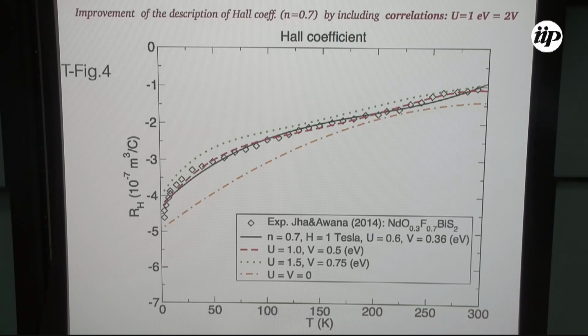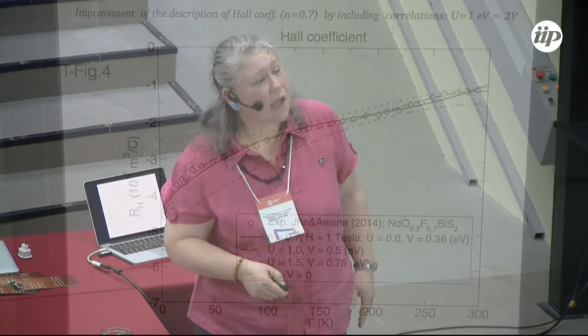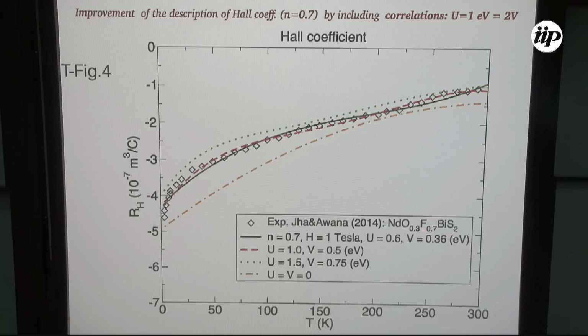Let me show you the kind of Hall coefficient results we're getting. Here the orange dot-dash curve is for the uncorrelated case. This is actually for another material, since we couldn't get Hall coefficient results for the lanthanum one, but this is what we got. So we can really do the calculation with the doping and tune things to adapt it. Here you see that the description of these open points, which are the experimental results, is better for some intermediate value of correlation. Not the smallest one, not the larger one, and not the uncorrelated.